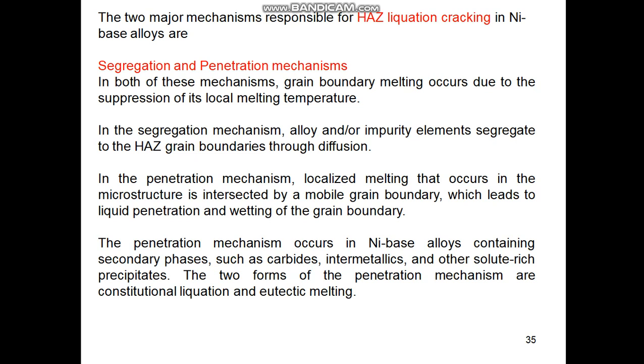And in the second mechanism, in nickel based alloy containing some secondary phases like carbides, intermetallics, and other solute rich precipitates, there will be a constitutional liquation and eutectic melting will take place. In the case we just discussed, the NbC, niobium carbides, it is a kind of constitutional liquation, and because of low melting point elements like sulfur and phosphorus, eutectic melting will take place. So here is an example of ductility dip cracking, which occurs in a thick section multipass weldment. You would see a thick section which is welded, and you will literally see a crack.